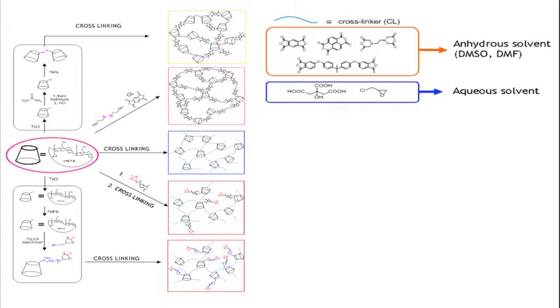Ibuprofen is dissolved in the solvent, so it's able to penetrate the polymeric network. And what we get at the end is a hydrogel containing the ibuprofen. The next step is to get rid of the water. And to do this, we can lyophilize the hydrogel. And eventually, we obtain a dry polymer, which is loaded with the ibuprofen. Very interesting. What's next? So there are important issues to be addressed now.